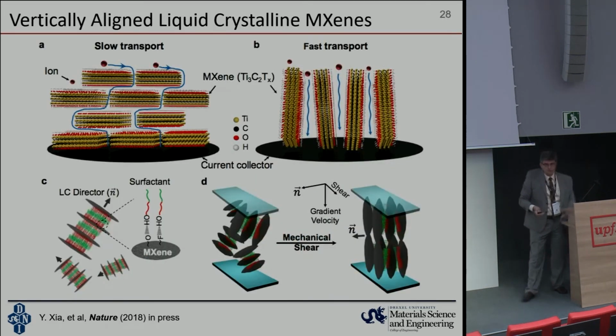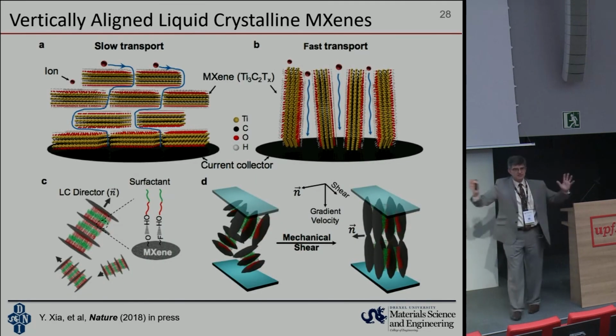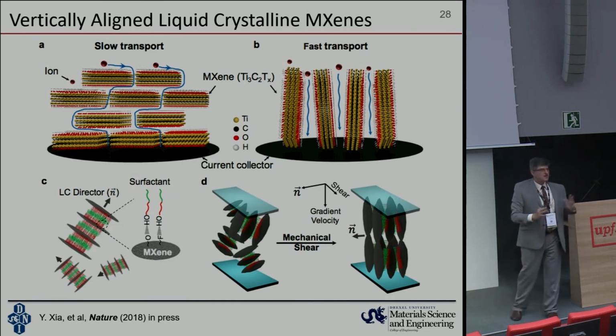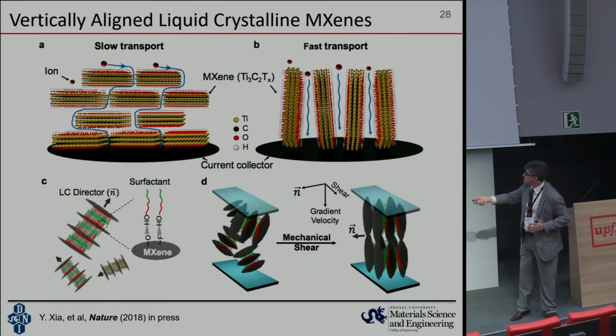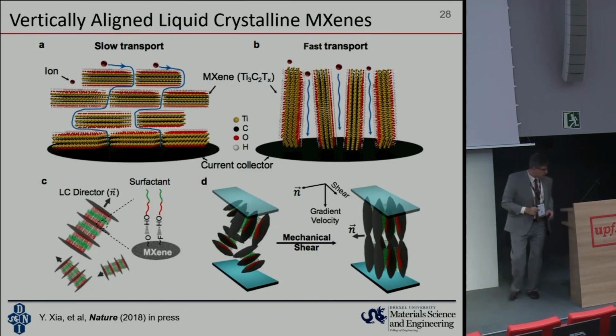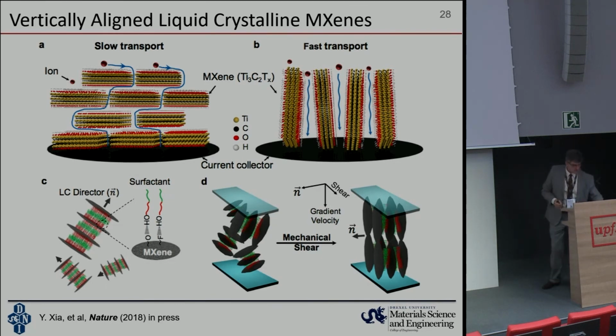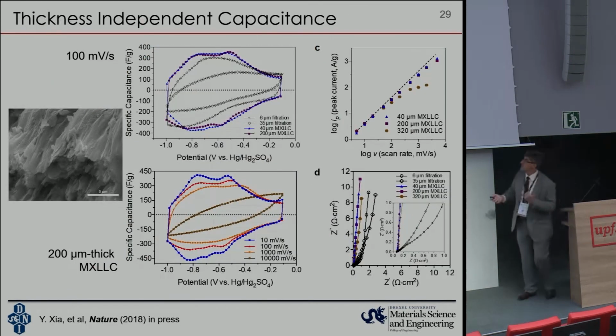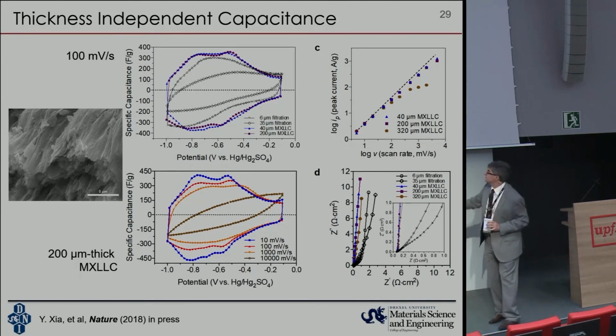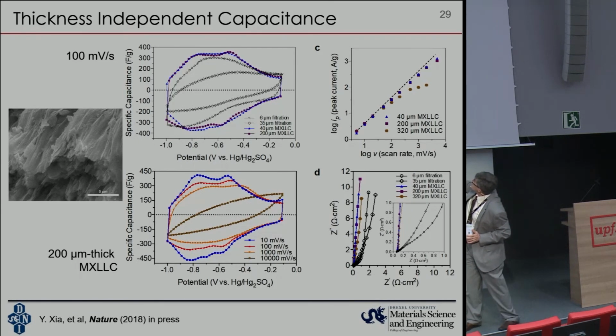And recently we also learned how to align these flakes vertically by using a liquid crystalline approach. Since I have no time left, I won't go into detail, but this paper should be in press in about 3 weeks from now. I just got page proofs today, actually, showing that if we have vertically aligned flakes, we can have a 35 micron film or 40 micron film or 200 micron film, and we pretty much have the same cyclic voltammogram.